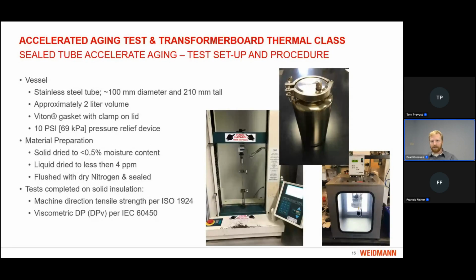After the aging periods for each of these vessels, the solid material is removed, and then the machine direction tensile strength is tested on both the paper and the pressboard, as well as the degree of polymerization on both materials.